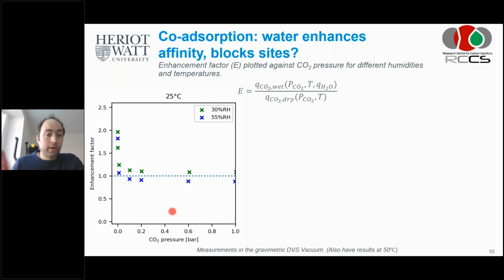And we have here first the results for 25 degrees and for 30% relative humidity and for 55% relative humidity. On the horizontal axis, we show the CO2 pressure in bar, and on the vertical axis, we show the enhancement. And an enhancement of 1 means that the same amount of CO2 is adsorbed in wet conditions as it is adsorbed in dry conditions.